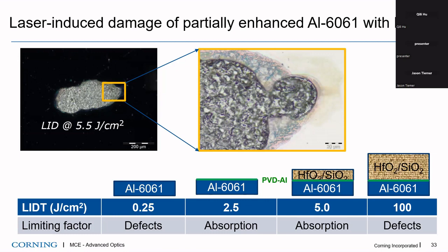My question was: is it a thermal effect or a field effect? I think when you have more layers, it's still the field effect. If you have fewer layers, since the coating hafnium and silica are absorption free at that wavelength, and aluminum has about 95% reflectivity, so 5% is absorbed, it's a thermal process, I think, with less enhancement.